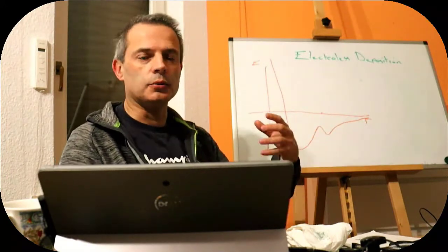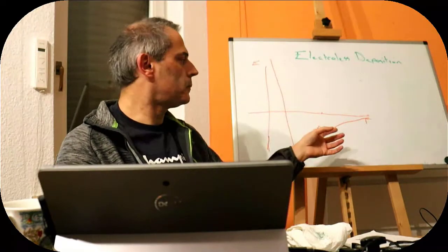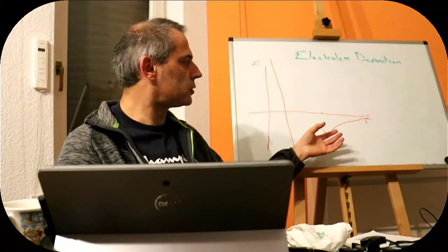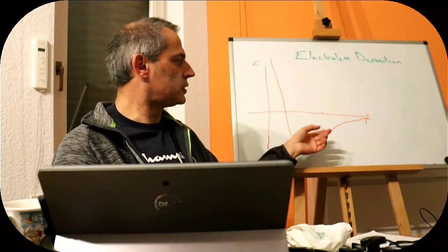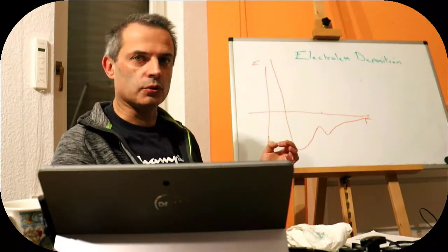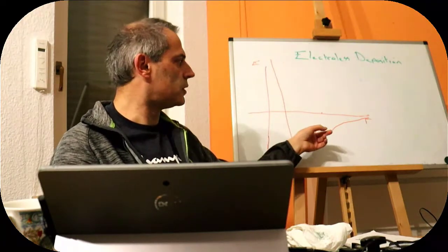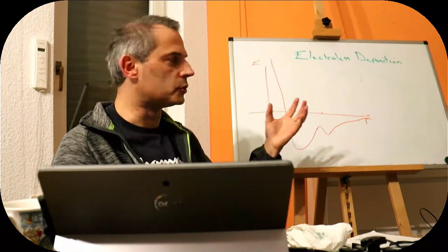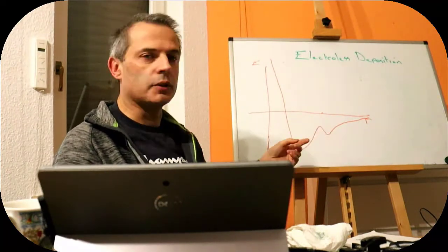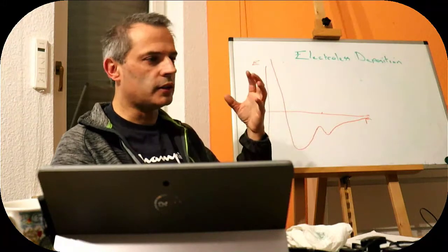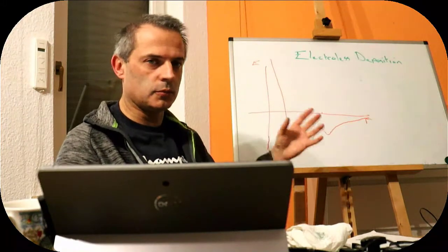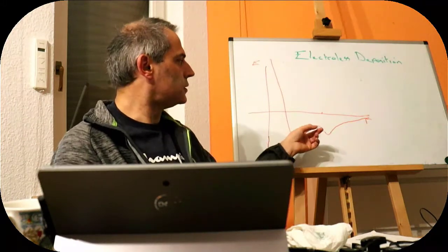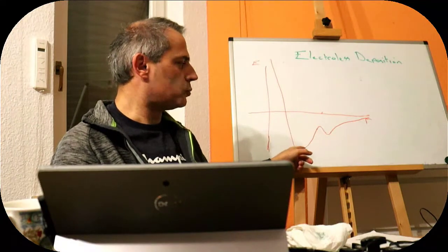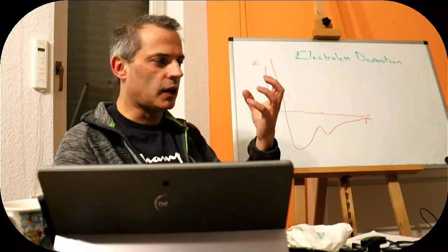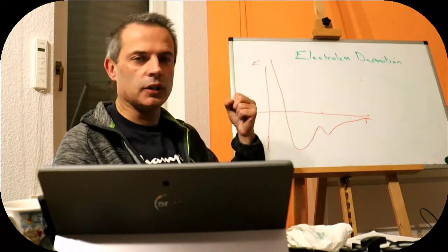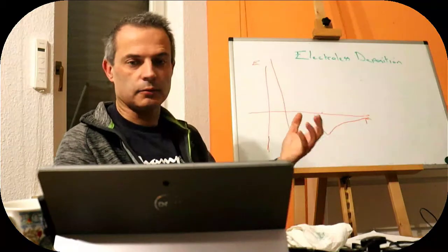If we manage to beat it in some way, so typically with an atomic force microscope we just push. In this case we are drying the water out, so we're using a different way of getting rid of these molecules that are forcing it apart. Then it can drop into the primary minimum, where the two surfaces interact directly. So this is where, as we approach, we get closer and closer, and the metal ion atoms interact with the silicon and oxygen.